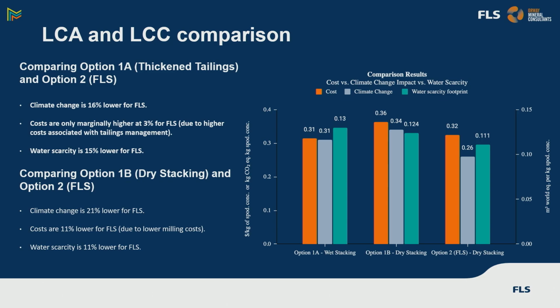And we found that if we compared our flow sheet to the conventional wet flow sheet, we got a 16% lower climate change impact. We increased the life cycle cost by 3%, primarily because we were going from wet tailings to dry tailings. And then we reduced the water scarcity by 15%, and we were using the AWARE process for that. And then if you compared it to the conventional flow sheet with the dry tailings, we reduced it by 21%, the climate change impact, 11% for the cost, the life cycle cost, and 11% for the water scarcity.